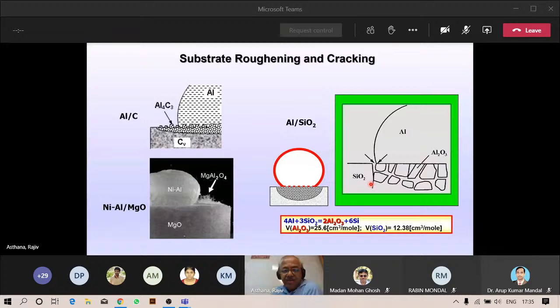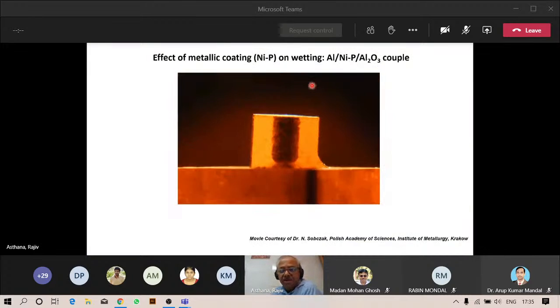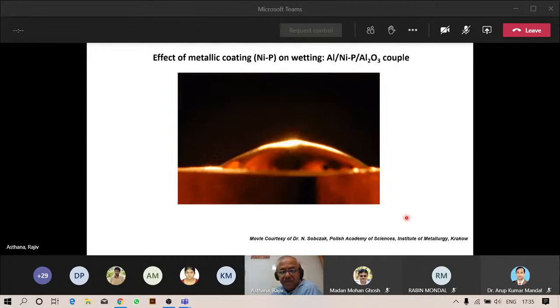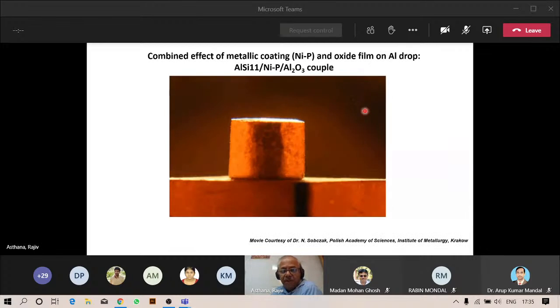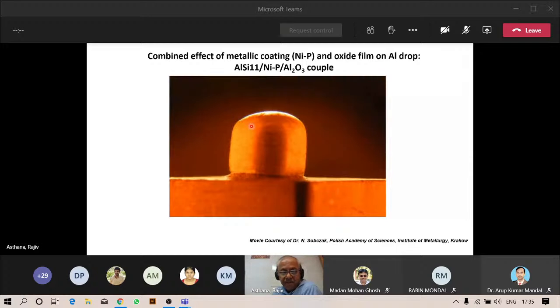Here you're looking at a movie of how aluminum spreads on aluminum oxide that has a coating of nickel phosphorus. So this is under very controlled condition, and you can see that aluminum will wet a phosphorus plated aluminum oxide surface because you form low contact angle. Look at the next situation here, where you have an oxide film on the liquid droplet. So you can see that oxide skin is very tenacious, and the liquid aluminum is melting underneath and trying to spread out.